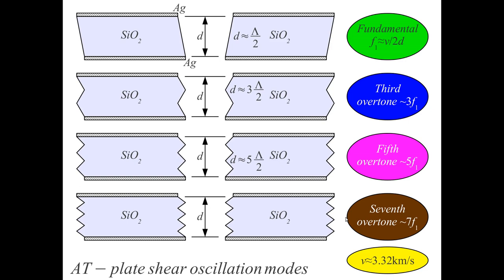If we look, so this is the oscillation of our crystal. The crystal usually has silver electrodes. There may also be gold electrodes or other metals plated on top and on the bottom of each crystal plate. Because of these electrodes, the overtone resonances are not exact harmonics of the fundamental frequency. Because these metal electrodes imply a mechanical load, and this mechanical load shifts all the resonances, but it shifts the fundamental more than the third or the fifth or the seventh overtone. So the major shift from the electrodes is on the fundamental frequency.